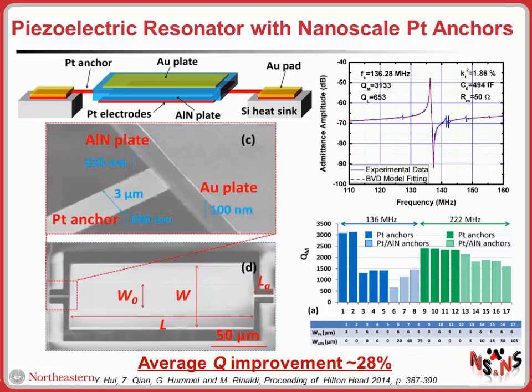Of course, this is not large enough statistical data to be conclusive, but it definitely looks like by using these very tiny anchors, basically having this large acoustic mismatch between the piezoelectric resonant plate and the anchor itself, helps in confining the acoustic energy in the resonant body of the device. So we can basically achieve very large thermal resistance, but at the same time, high quality factor and good electromechanical performance in general.